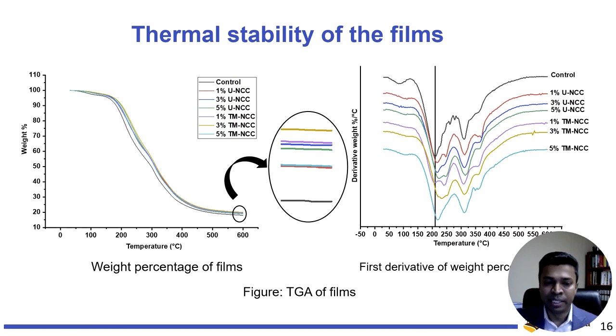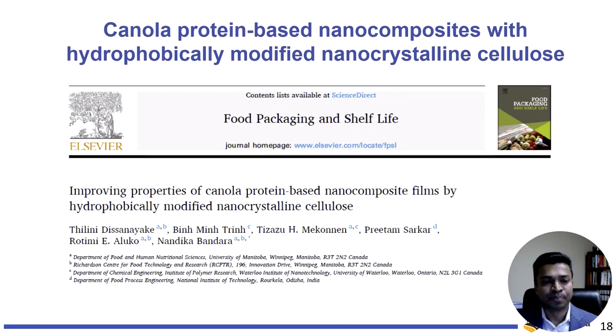We did take a look at the thermal stability of the material as well. With the addition of the nanomaterial, we identified the material is more thermally stable in the thermogravimetric analysis. So in the first study, what we focused on was trying to improve the dispersion of the nanomaterial. We did see a big improvement in the material properties, but at the same time, some of the properties we wanted did not improve in the same way.